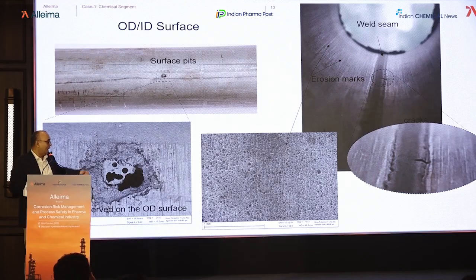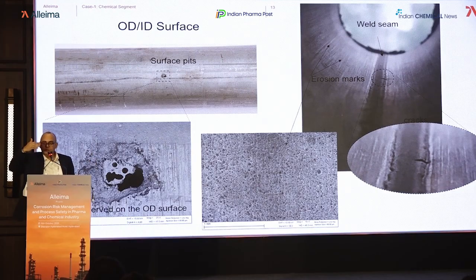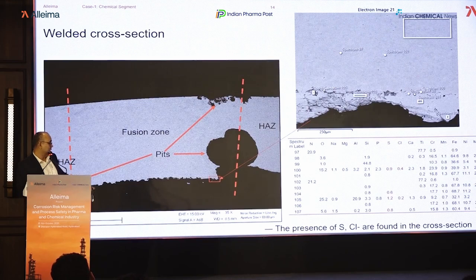From the ID side, the inner surface, you can see that there is a seam, and on that seam you have some cracks, and you can also see some groove features. Whenever you have a groove feature, that is a sign of erosion, so your material is basically being removed. And there were a lot of pit marks also. Wherever there was a crack, we took a cross-section, a transverse section, and what we could see is that there's a big pit in the welded area.